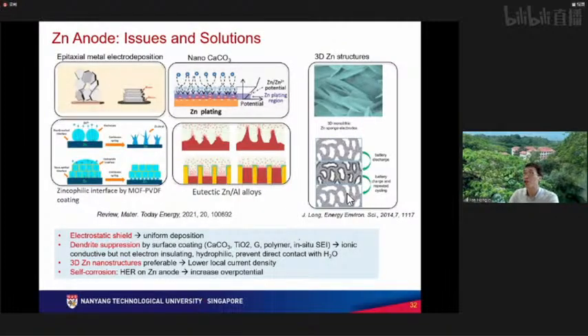So to deal with these challenges, people do various things. One can do epitaxial metal electrodeposition of zinc on epitaxial graphene sheets. Another is a paper published in Science by Professor Zhi Chunyi from City University of Hong Kong, where they coat a very thin, porous calcium carbonate inorganic layer on the surface to tune the interface potentials. Another is a MOF and PVDF polymer coating, an organic plus polymer coating on the surface. It is a very flexible and soft surface, which allows the zinc ions to penetrate through and isolates direct contact with the water. There's also a three-dimensional eutectic zinc-aluminum alloy with a three-dimensional hole structure, and these holes have an electrostatic shielding effect, so the zinc does not just go to the sharp points but spreads uniformly.